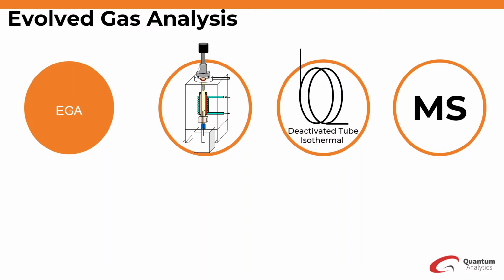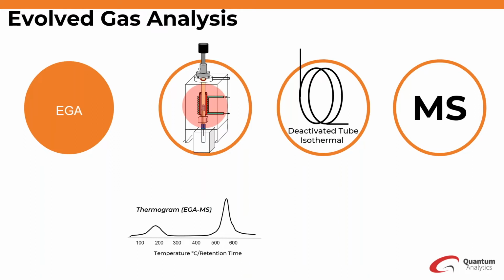As I've mentioned, often we begin with an evolved gas analysis. In EGA, we have your pyrolyzer, which is on top of your GC, with a deactivated metal tube kept at an isothermal temperature that feeds straight into your detector, MS in this case. When the sample cup is dropped into the furnace, the temperature is ramped, and while that's happening, all of your pyrolysates are going through that tube and collecting at the MS. So what you get at the end here is this nice thermal profile of your sample, which we like to call the thermogram. And don't forget, at each point in the curve, you can collect the mass spectrum. This EGA thermal profile will really facilitate how we navigate the other modes of operation.